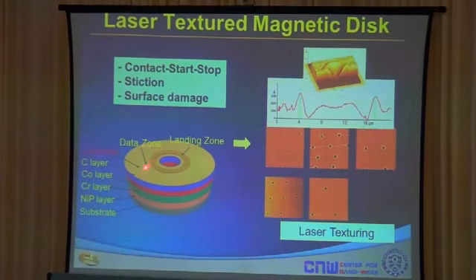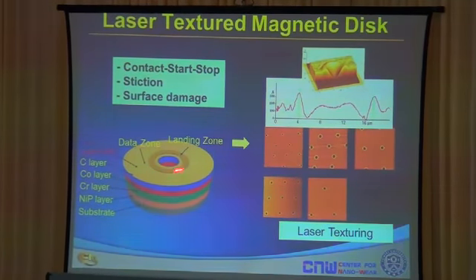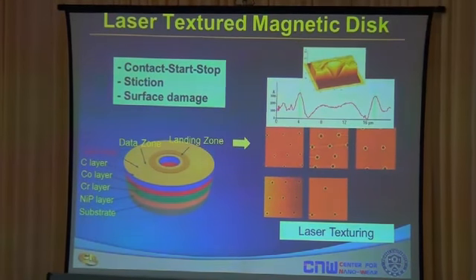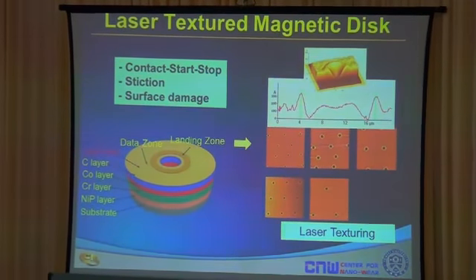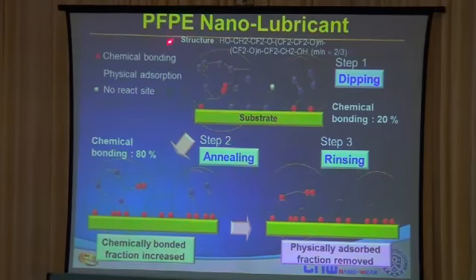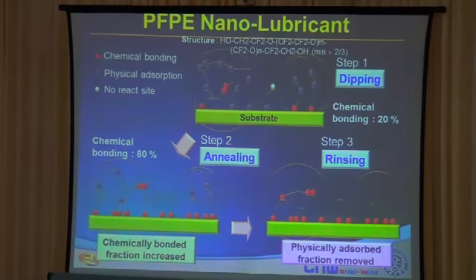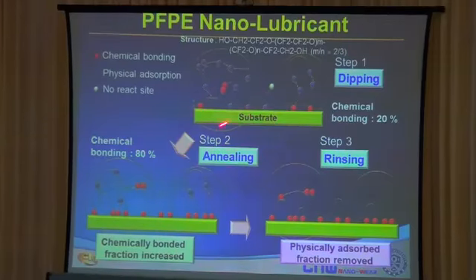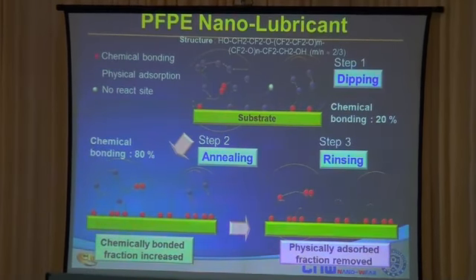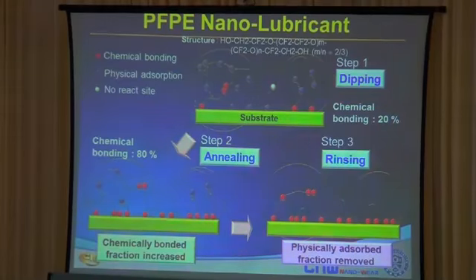And when you turn off the computer, the slider will go to the landing zone and park there and settle down on this track. Of course, the wear of these tracks will be very important because it is sliding against the slider as the speed lowers. And lubricant is used, PFPE. Perfluoropolyether is a lubricant developed for this purpose. It's a fantastic lubricant with a thickness of only about 1.5 to 2 nanometers. So it's not like a liquid lubricant that we use in ordinary machines. It's a very semi-solid-like lubricant that's coated on the substrate by a dipping process, so you have a solution and you dip the disk and it's automatically coated on the surface.